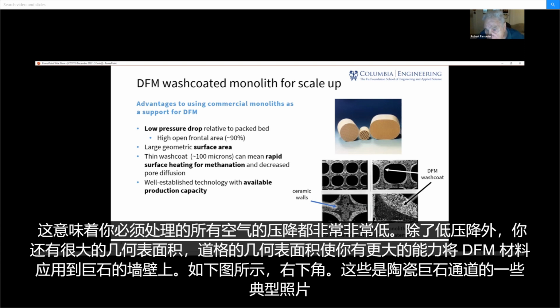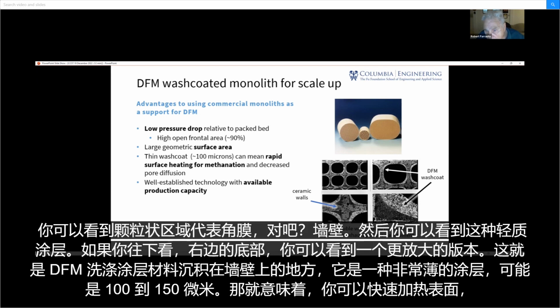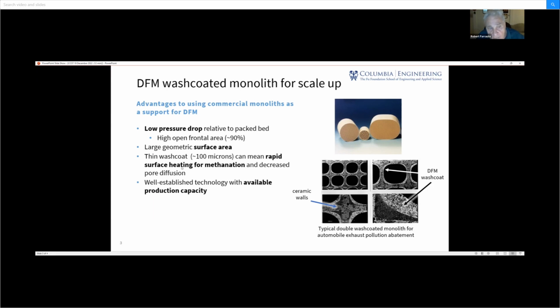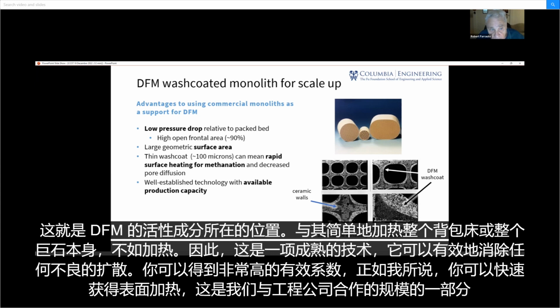These are some typical pictures of the channels of a ceramic monolith, and you can see the grainy area represents the cordierite, the walls, and then you can see this light coating, and if you look down here on the bottom right, you can see a more amplified version of that. And that is where the DFM washcoat material is deposited onto the walls. And it's a very thin coating, maybe 100 to 150 microns. And that means then that you can rapidly heat the surface, which is where the active components of DFM are, rather than simply heating the whole packed bed or the whole monolith itself.